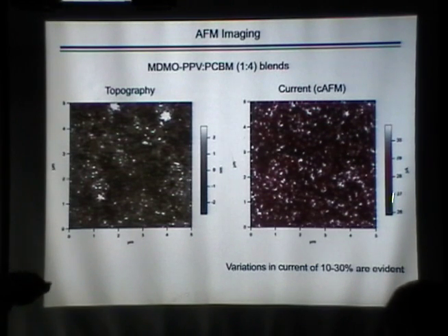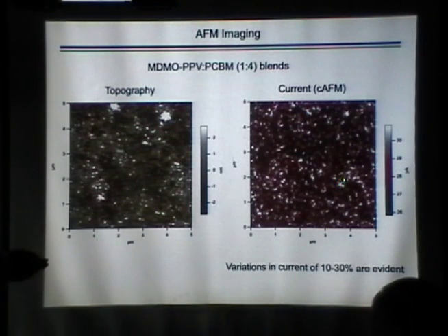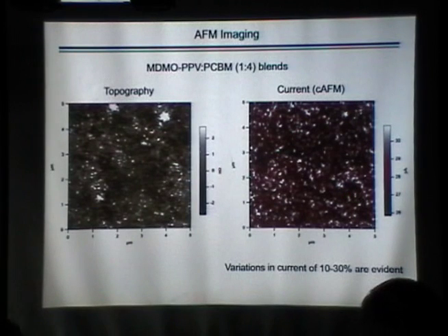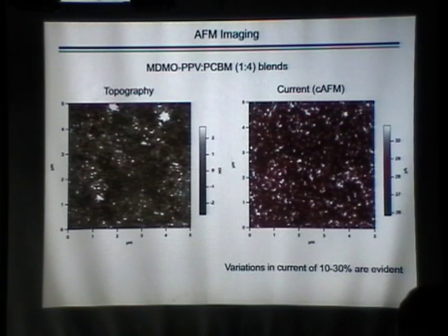Current is measured in picoamps. And we see some spots here that are close to 30 picoamps and others that are about 25. So we have actually variations up to 30% across the surface of the film. So we have a lot of work to get this to be a nice uniform distribution of current that we think we would want for the material. So that just gives you an idea.